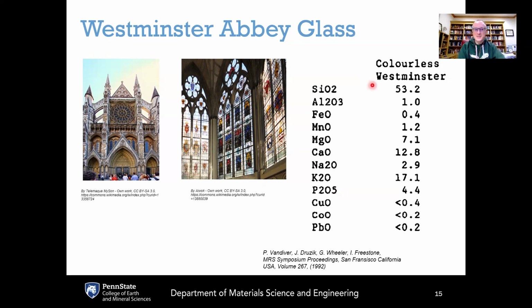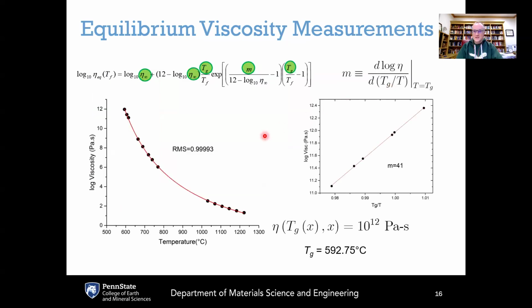We got the recipe here for making colorless Westminster Abbey glass. This is the composition of Westminster Abbey glass. And you can see it's quite a bit different from modern soda-lime silicate glass in that it is lower in silica. It's quite high in calcium, but it's really high in potassium. So the sodium is a lot lower than modern soda-lime glass, but the potassium is much higher. It also contains some phosphate and a bit of manganese. We made our own Westminster Abbey glass following this formula, using the same raw materials that were used in medieval days. And we measured the viscosity.